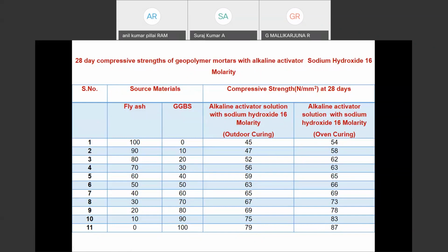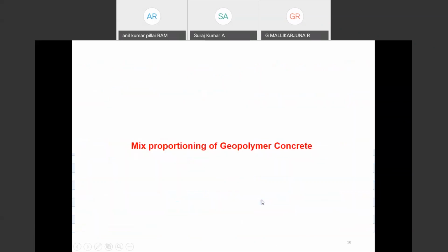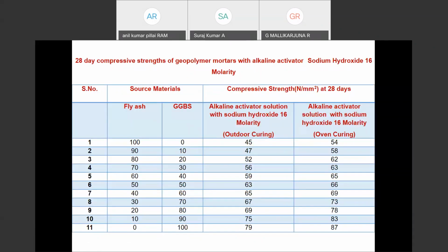Whenever we increase the concentration of sodium hydroxide, the strength increases. Whenever we increase the GGBS content, the strength also increases. This is about what we first identified: how much alkaline content is required for the preparation of this fly ash and GGBS paste. After that, the main site-condition problem is setting. With a higher amount of GGBS content, the setting problem arises, while strength increases with increasing GGBS content and sodium hydroxide concentration.